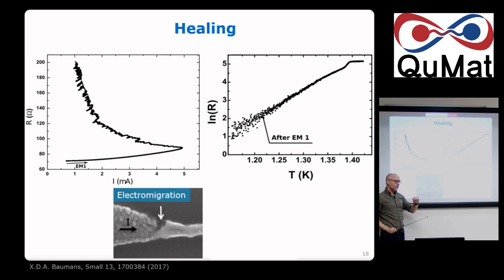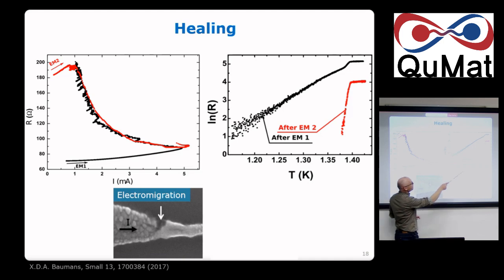But now instead of sending the current like that, we reverse the current. Okay. And what's going to happen is we send back the atoms we took from here and we put them in the same place, which is kind of astonishing. Let me show you. So this is what happened. We started from that resistance and now we anti-electromigrate, we call it healing, and then you go all the way down. And then you recover a very nice transition.